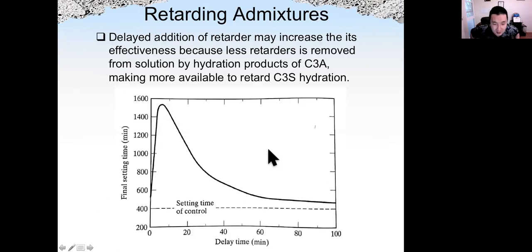And here is an example. Some people tested how delayed addition of retarder can change the final setting time. So delayed addition of retarder increases the effectiveness of retarder, because less retarder is removed from solution by hydration products of C3A.